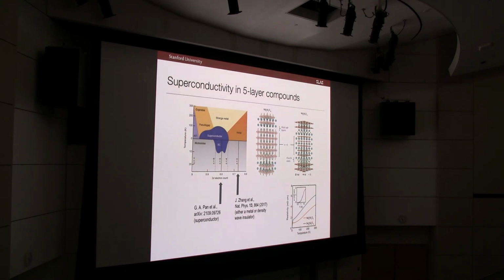In fact, this thinking has already been around. This was work from Argonne National Labs, where they had studied in detail the n equals 3, or tri-layer, phase. What they found was, depending on the composition, either a metallic or a density wave insulator ground state. And they speculated that maybe they have gone too far in doping. But actually, if you go to n equals 5, you would live nominally in the superconducting dome. And first reports seem to indicate that indeed these 5-layer compositions are superconducting.